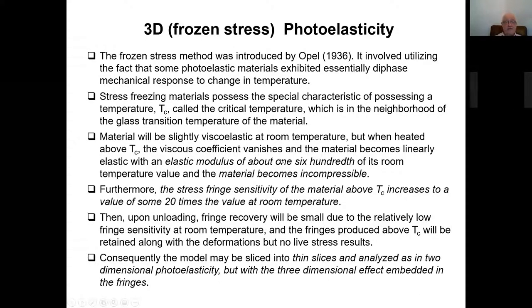The modulus of elasticity becomes about 1/600th of its value at room temperature. So 1/600, and the material becomes incompressible. And the stress fringe sensitivity of the material above Tc is about 20 times its value at room temperature. So this makes a difference. Essentially, you have to go slowly through this critical temperature, load the specimen, whatever you have, and then go back and freeze the deformations. Although it's called the frozen stress method, you are freezing the deformations, and you can analyze thin slices as in two-dimensional elasticity, but you have a three-dimensional effect embedded in these fringes.